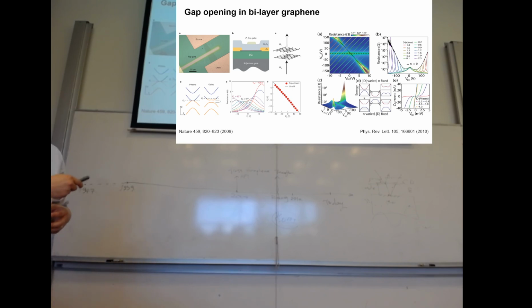So this paper, if you look in the literature, reports almost the highest resistance we can find, like 1 gigaohm. 1 gigaohm is really insulating. It means if you put 1 volt on top of this graphene, you have only 1 nanoampere of current. So it's very insulating. But the bad thing is, again, all these insulating areas are very localized. If you scan the gate voltage, there is only a peak. So for application-wise, we don't want that.